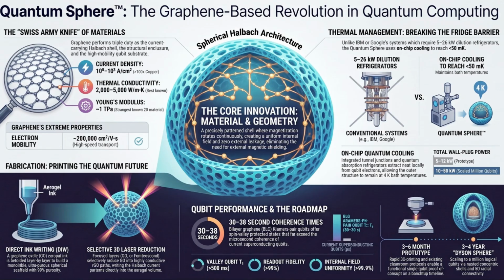That's insane. Then there is the electron mobility, which sits at around 200,000 square centimeters per volt second. The thermal conductivity is 2,000 to 5,000 watts per meter Kelvin, which is literally the highest of any known material. It can move heat incredibly fast. Yes. And on top of all the electrical and thermal properties, it is physically the strongest known two-dimensional material with a Young's modulus of about 1 terapascal. Let's translate that Young's modulus of 1 terapascal into physical reality, because that's the number that really makes this entire architectural leap possible.